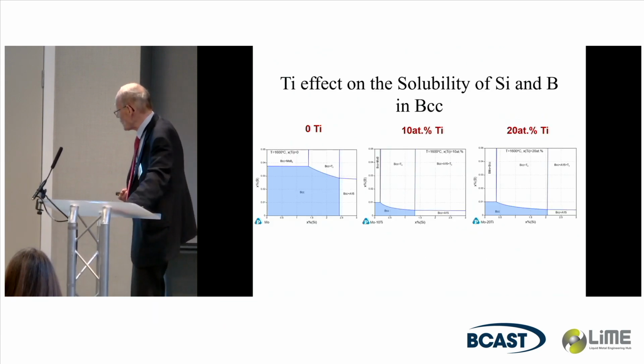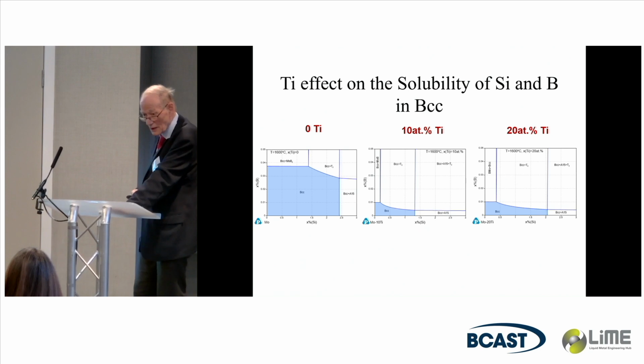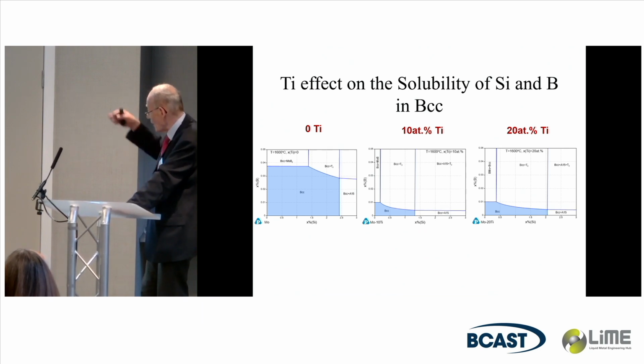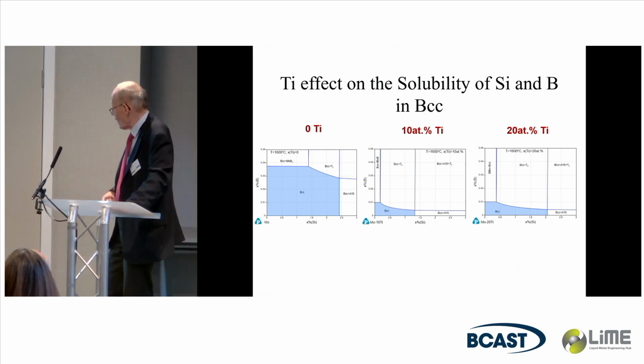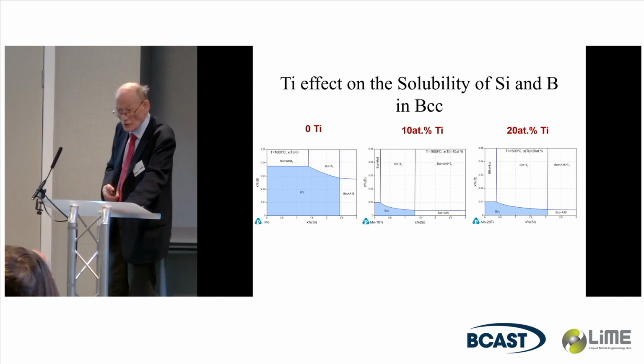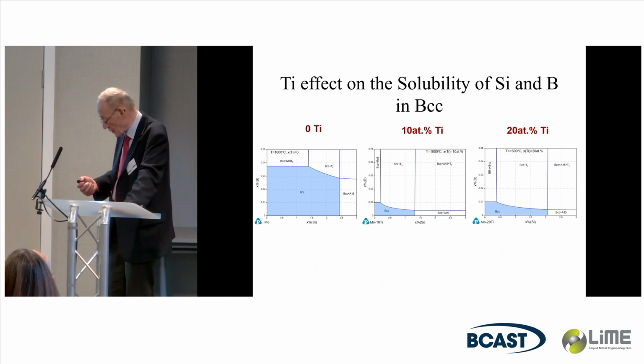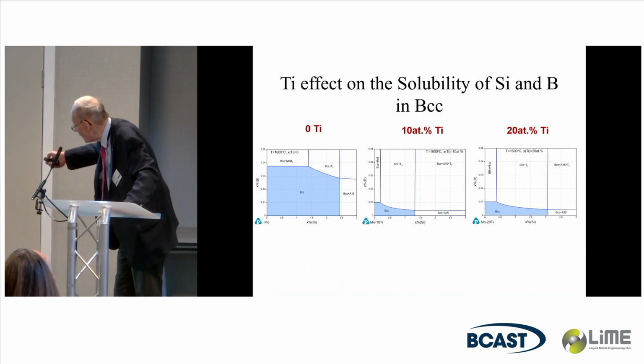The other advantage is that we had to reduce the density to below 9. So we added titanium, and my colleagues at Computherm pointed out that with 10% titanium, we can even reduce the silicon solubility further. So now it's over here, it's about 0.2%.